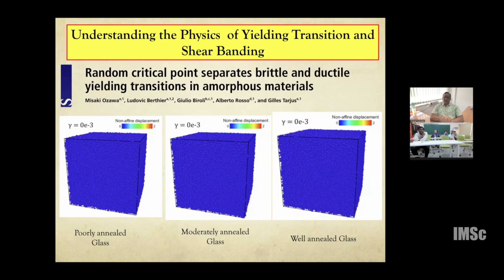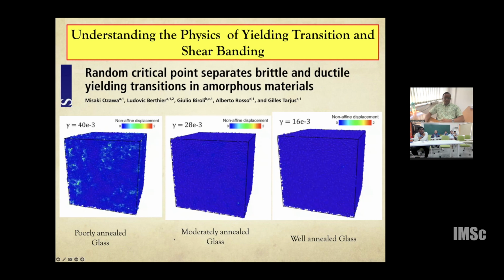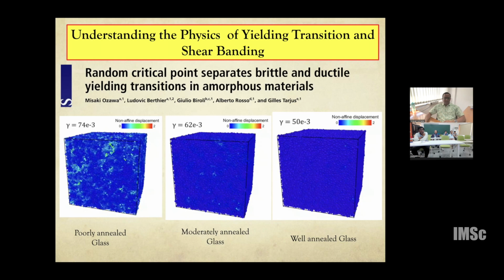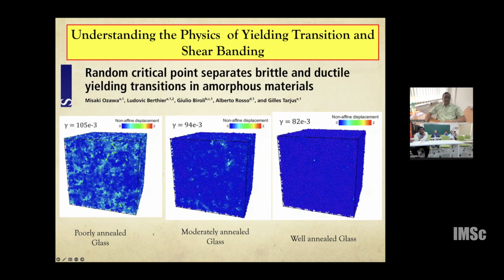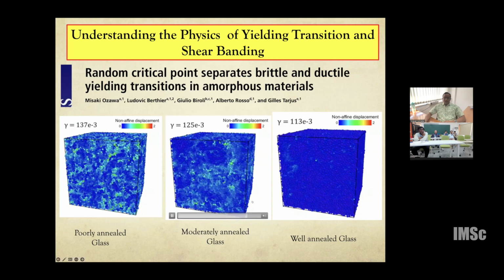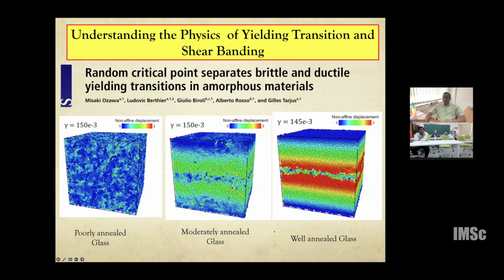So now with these advances, we are in a phase of glass which can be compared directly with an experimental glass at least. And what people did was take these glasses, which are called ultra stable glasses, and shear them. So I'm basically playing three movies. The extreme left one is for a poorly annealed glass, and you see that there are a lot of plastic events happening in various parts of the sample. The middle panel is a moderately annealed glass, which you can achieve even with simple molecular dynamics simulations. But on the extreme right, you have a well-annealed glass prepared with swap Monte Carlo.